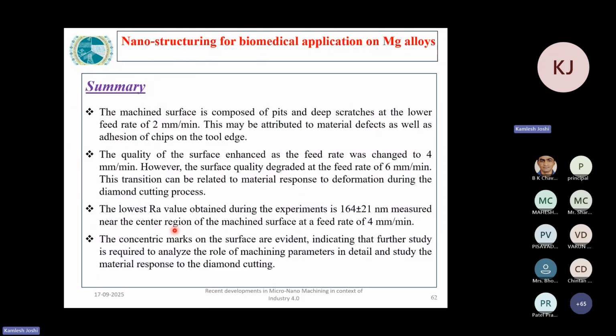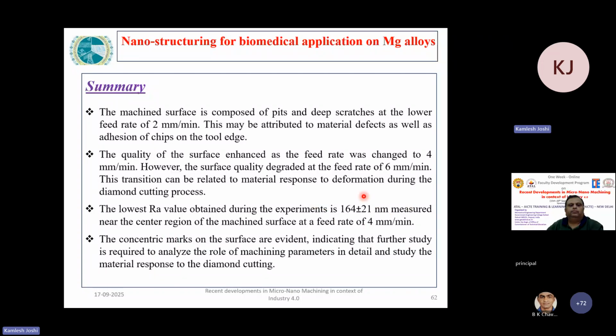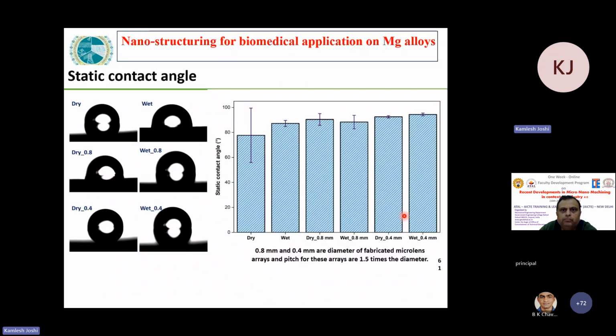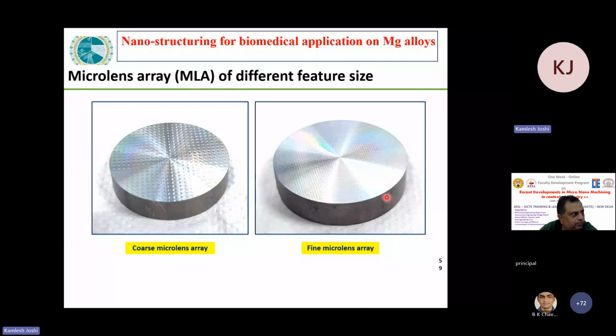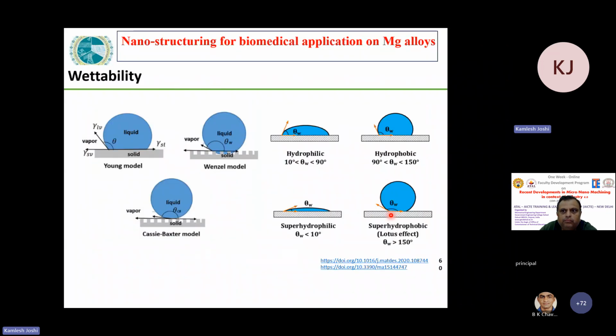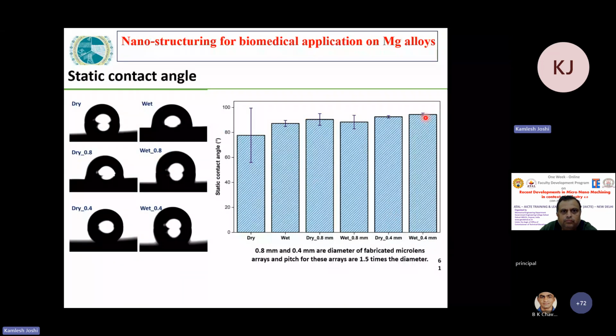implant life. This is the summary: the best roughness which was achieved in this work was around 164 nanometers at a feed rate of 4 mm per minute, and then the surfaces were produced in the form of micro lens, and a contact angle of around 100 degrees was obtained in the work.